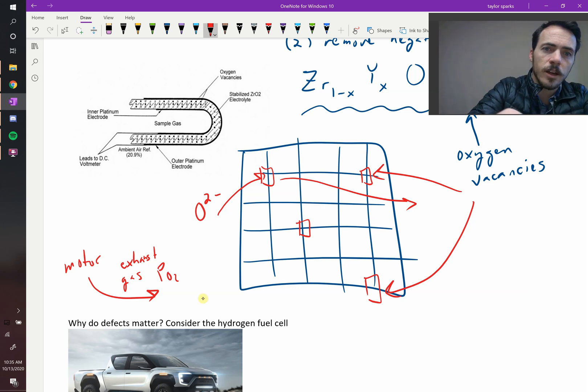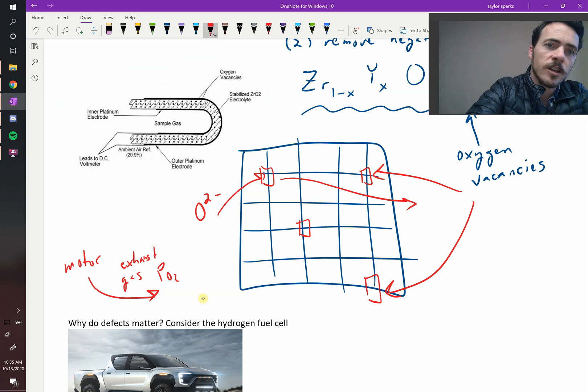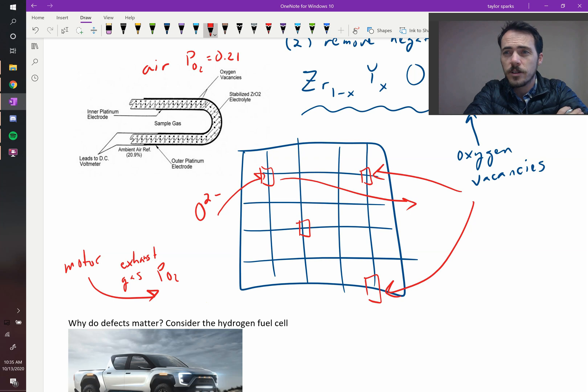So you want your partial pressure of oxygen to be close to zero. That has some partial pressure of oxygen. So how do you measure that partial pressure of oxygen? Well, you stick a sensor into it. So this is your sensor that sticks into the exhaust pipe of your car. And you have, on the outside, you have air. So PO2 out here is equal to 0.21, 21% of air is oxygen. But in your sample gas, this is where your exhaust goes, you would like it to be as close to zero as possible. So if there's no oxygen on the inside of that little tube and there's lots of oxygen on the outside, then there's a driving force because there's a difference in concentration. It's going to want to go from the outside air into your sensor by traveling through this barrier. If that material is made out of stabilized zirconia, the same thing that we just talked about, zirconia that you've put some yttrium into it, it will have oxygen vacancies. Then you can actually get oxygen traversing through that barrier and you'll be able to measure what the partial pressure is inside your exhaust gas.